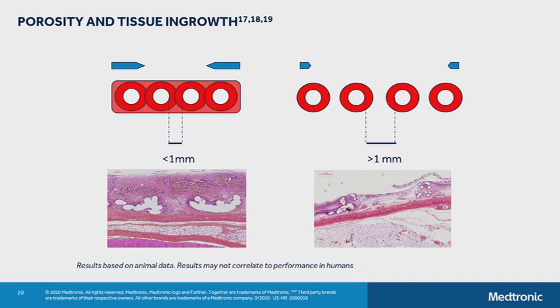Speaking of the macroporosity, the mechanism for this mesh shrinkage, as we've often heard it, is a contractile force that arises from the fibrous capsule that can form when the inflammation from the fibrous bridges around the individual filaments becomes too close. This happens when you can have less than 1 millimeter in pore size. As you can see from this histology slide here, the actual inflammation around these monofilament structures merges with the inflammation around the other bundle of monofilaments. When these combine, they can create an encapsulation, and this fibrous bridging will serve to constrict the mesh and shrink it, appear to shrink it at least.